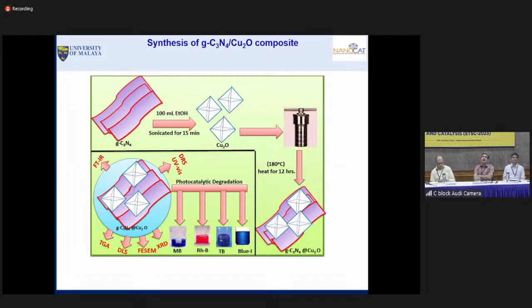We did this one with the solvothermal method. Graphitic carbon nitride was added to 100 ml of ethanol and sonicated for 15 minutes. You can see the beautiful morphology of copper oxide, and then we did the same for this. These two solutions were taken in an autoclave and heated at 180 degrees Celsius for 12 hours. Finally, we got this composite. After this, we did photocatalytic activity for methylene blue and different dyes, rhodamine B, thionine blue, and blue ink.